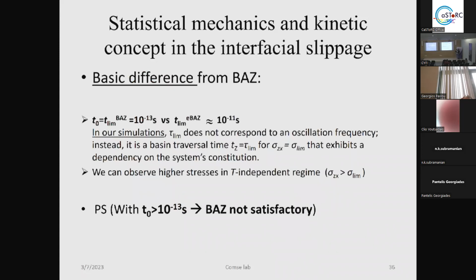The limit time, the tau lim that Zhurkov saw, was in the order of 10^-13 seconds, the oscillation of atoms. But we saw, at least in the epoxy pristine graphene, 2 orders of magnitude bigger. So we saw a numerical, let's say, disagreement.